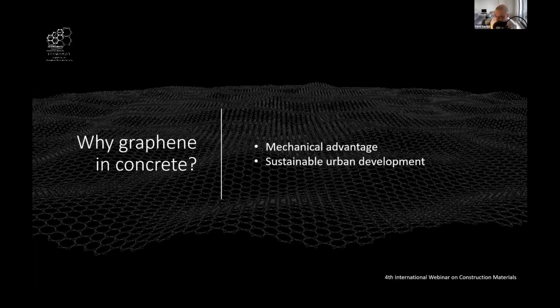The next most important question that you might also ask yourself is why we should put such an expensive material as graphene in concrete. It is expensive. And by the way, just so you know, each gram of high quality graphene is priced around $500. And you're going to need 3% addition by the mass of cement for an optimum result. I did the math for you. For each ton of concrete, you will need 10 kilos of graphene. And if you decide to reinforce your concrete with these nanoparticles, that adds up to $5 million for only 1 ton of concrete. And with 1 ton of concrete, you can only pour a small slab. So it is by no means a viable financial consideration.